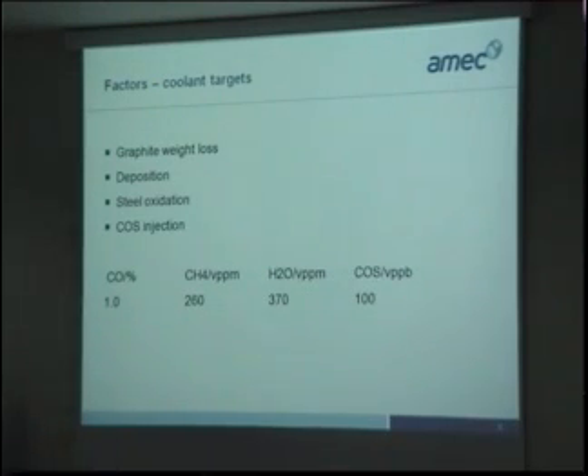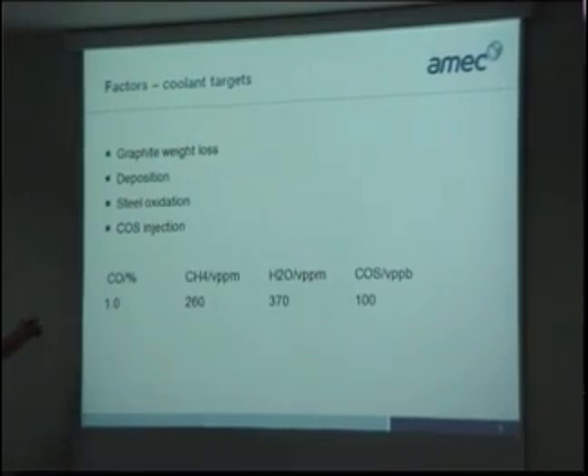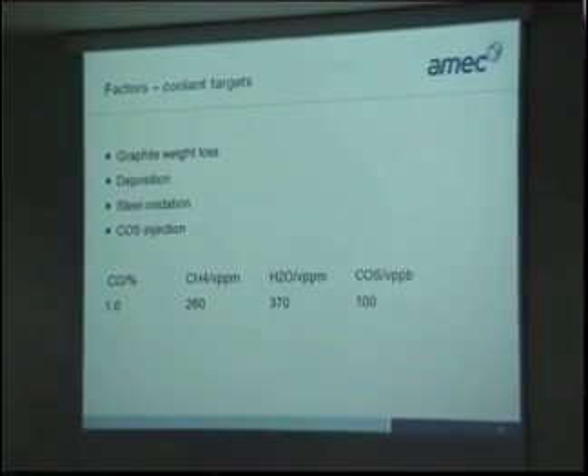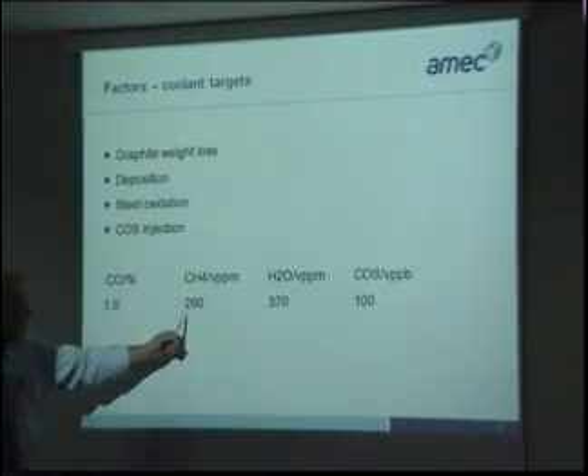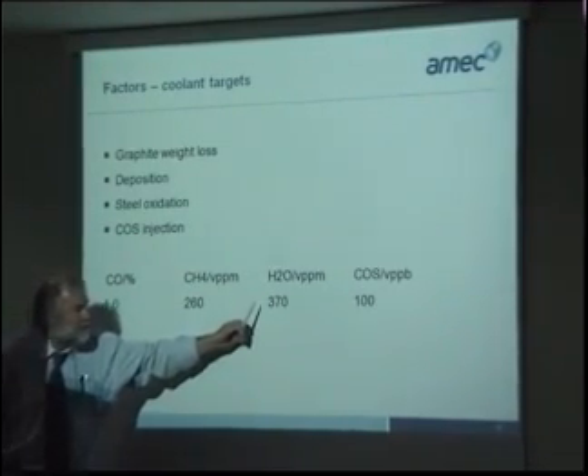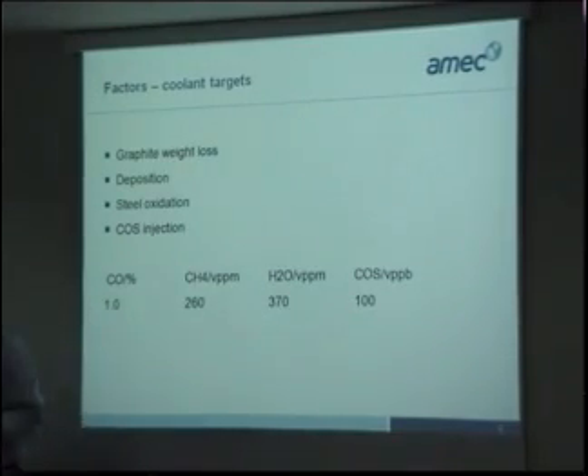Deposition is an issue, and that's brought about because of the carbon monoxide and also the intermediates that are formed. For example, ethylene, or ethene as I should call it, leads to carbon deposition on fuel and boiler surfaces, and that inhibits heat transfer. To mitigate that, we add carbonyl sulfide, and I'm going to talk a bit about that later. But just to give you a feel for the sort of levels we're talking about, with 1% here, 260 for the methane. Water's controlled using dryers in a bypass plant, and again I'll show you that in a moment.